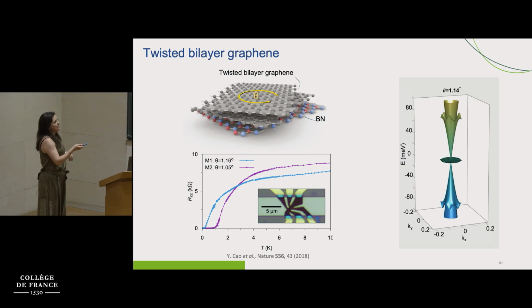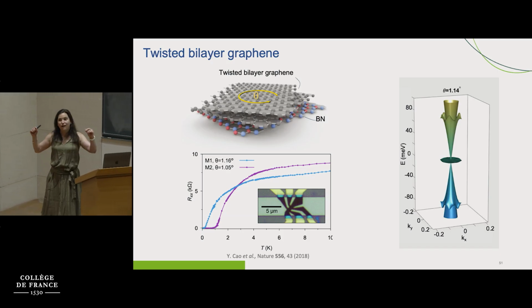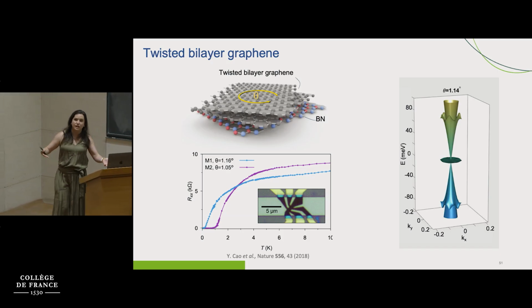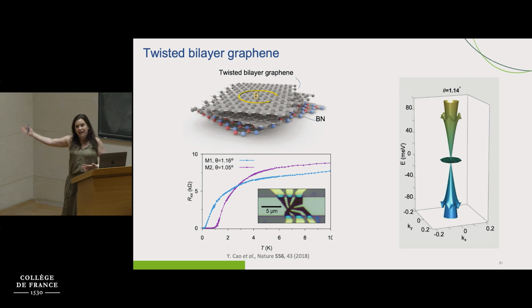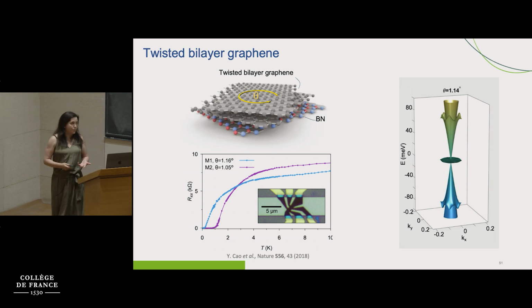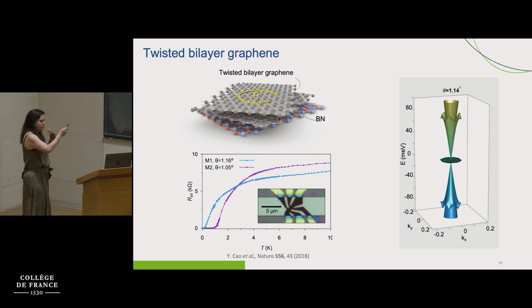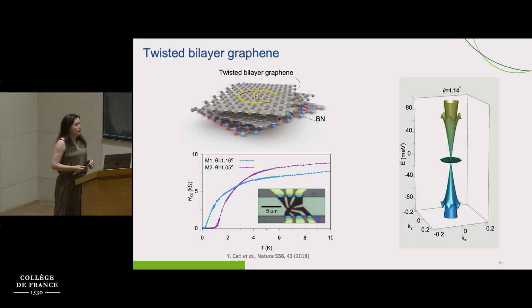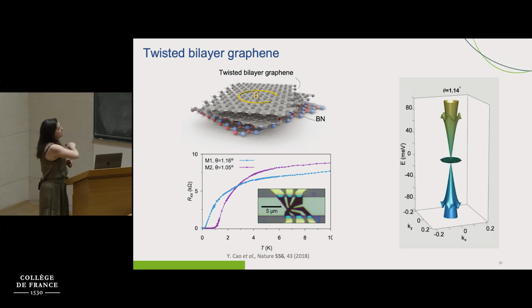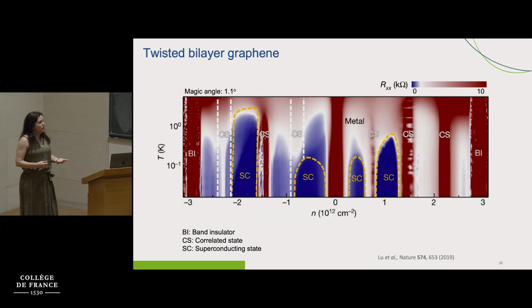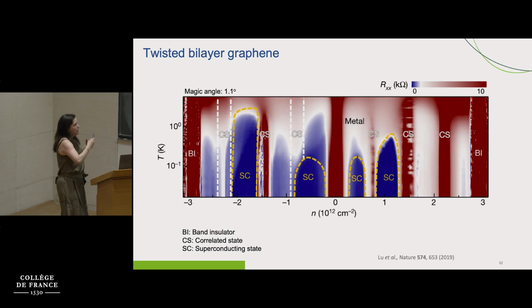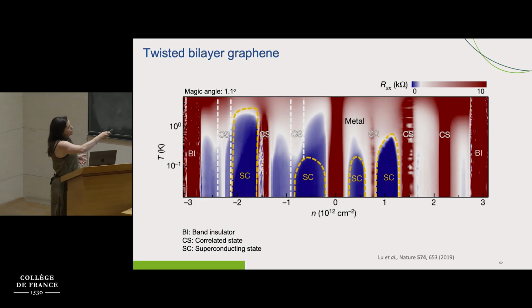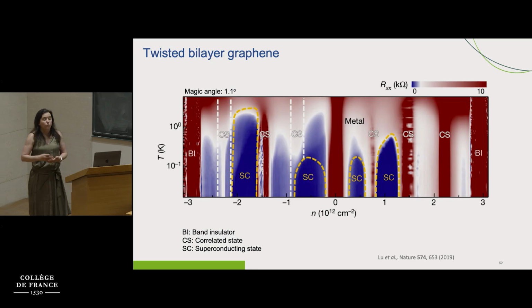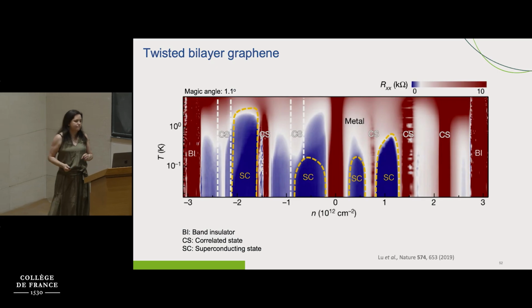And what is interesting here is that a flat band will quench your kinetic energy, and now your interactions are going to become much more prominent, okay? And that's why you get all these states. Of course, this was once again the first measurement, but not long after, a lot of new superconducting domes, correlated states, etc., were observed in the same system.